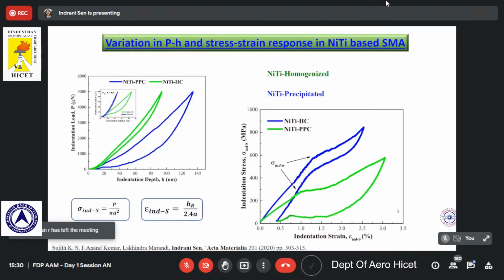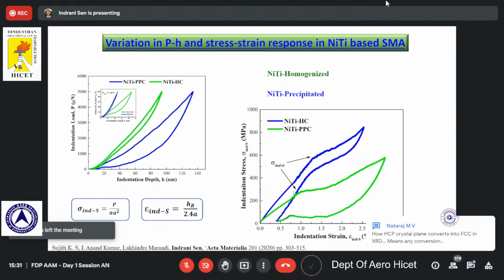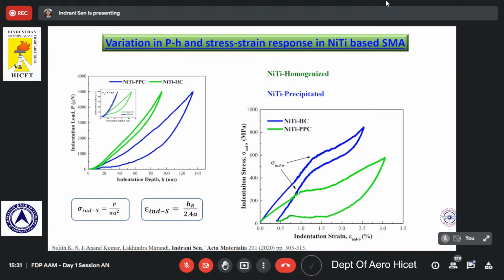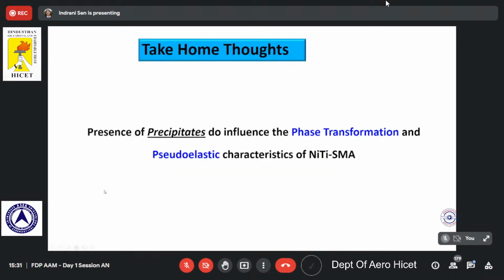The same curve is just shown here, but there is a complete difference in the stress strain behavior. In fact, the green one, the one with the precipitate, has required much lesser stress for the transformation from austenite to martensite, and it can show a plateau region also very distinctly. So this once again has shown the presence of precipitates. Same alloy content and everything, and also we are not here talking about the orientation or anything, even on the same orientation, just if we are having the alloy aged. So if there are precipitates forming in the structure, that can also influence the phase transformation behavior and the pseudoelastic recoverability.